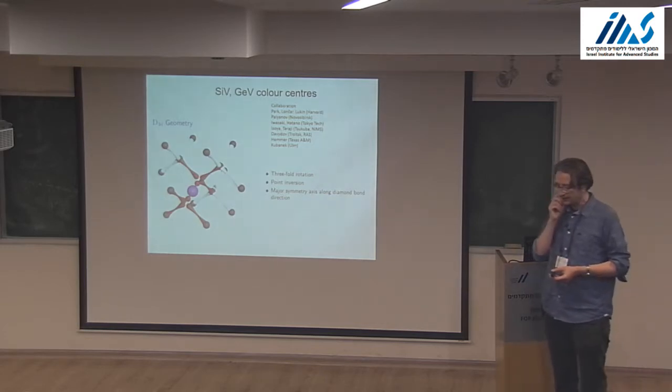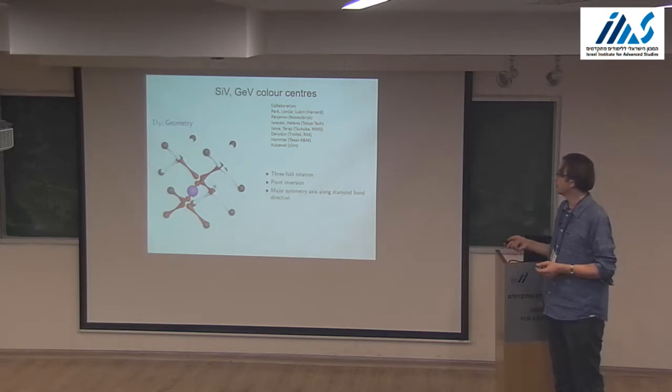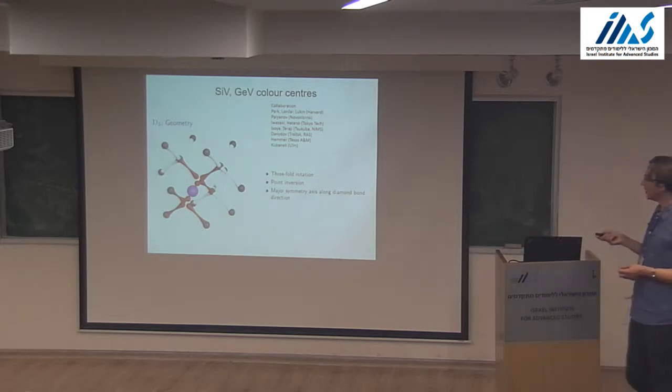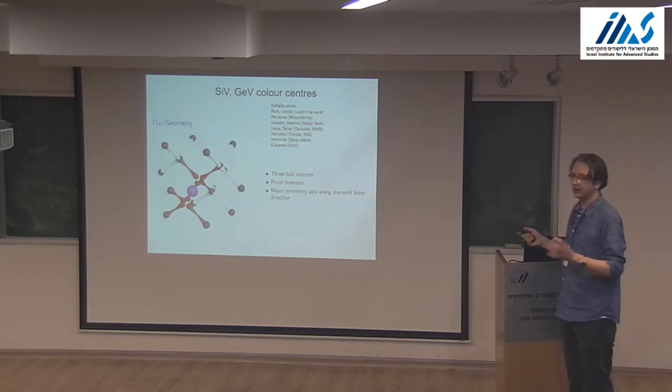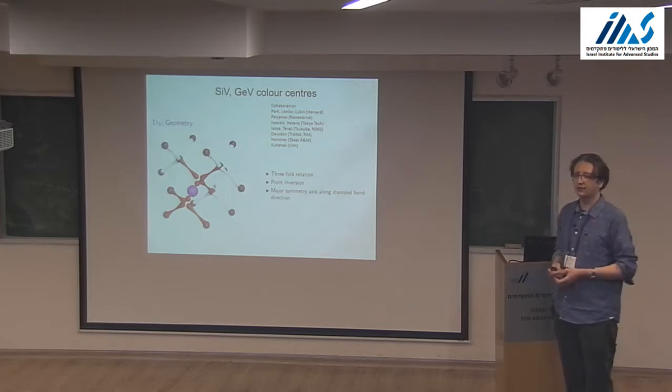So the design of new defects in solids will be about making structure more symmetric compared to NV center in diamond. Remember, nitrogen-vacancy center is a nitrogen sitting at a lattice position and vacancy nearby. If you take a larger atom, it will not fit very well to the carbon location.